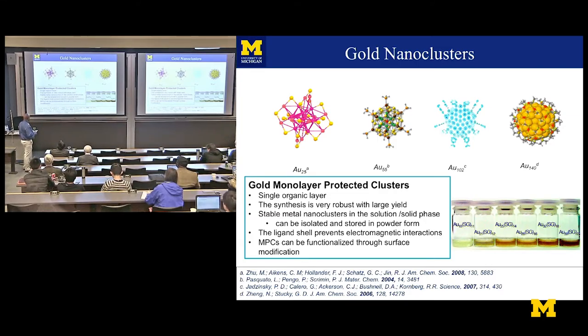They termed this gold monolayer protected clusters, and the idea is that they'd have a single organic layer, and the synthesis could be robust so that you can do this in the solution or solid phase. You could store it in powder, and then the ligands would prevent some interactions, and these clusters can be functionalized through surface modification. You can see there's the surface ligands on the outside of this.